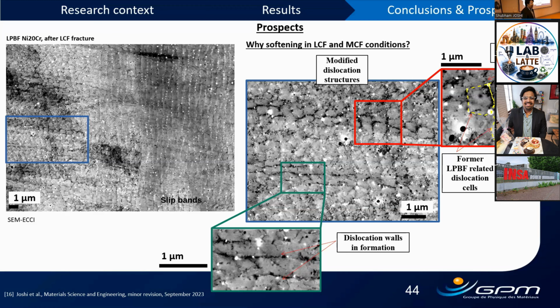If I did read the work, okay. Do you think that there is really a threshold for that actually? I think these thresholds exist, especially in the systems that I'm working with. Similar behavior was also seen for 316L, where the threshold was 98% of the yield stress. So it was quite high. I think it was your paper, I don't remember the name. Strain controlled, and so we also saw that in 316L.